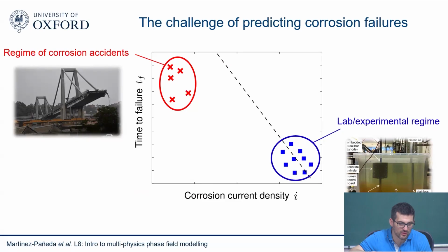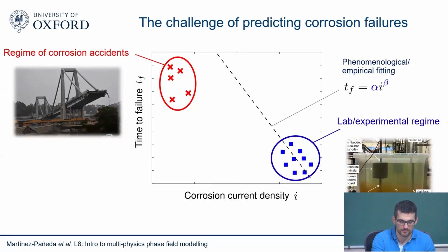So that is one of the main problems. We need to go from very fast experiments to other time scales. And of course, the way we extrapolate is that we get a bunch of data points and we fit the data. So you can imagine here a time to failure versus applied current density as a function of two fitting parameters, alpha and beta, that appear magically there, and that we just calibrate with experiments. But we don't know what alpha means, we don't know what beta means. We just pick units a bit randomly. So this is the problem, right? It's not as easy.